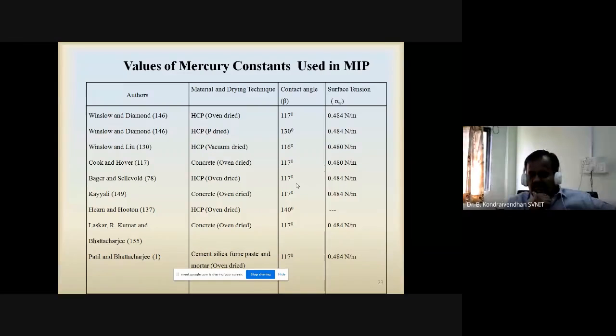For example, if you are using an oven dry, then we have to take the contact angle as 117 degrees and surface tension as 0.48 Newton per meter. If you are going for a pressure dry, then you have to use 130 degrees and 0.48 Newton per meter. If you are using a vacuum dry, then we have to take the contact angle as 116 degrees and 0.48 Newton per meter. So there are a lot of literatures available. Based on the literature, you have to choose the value, and accordingly insert it in the software also.